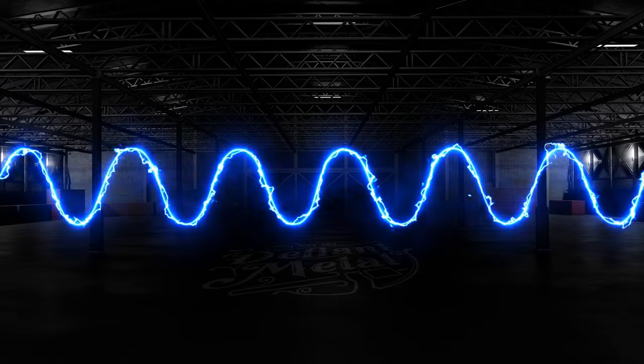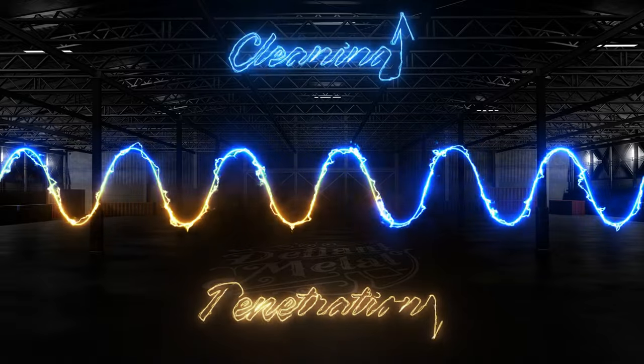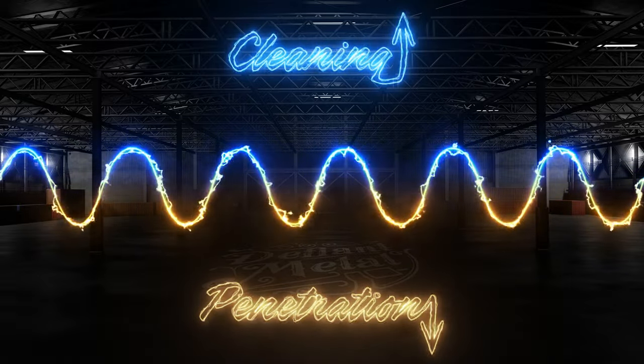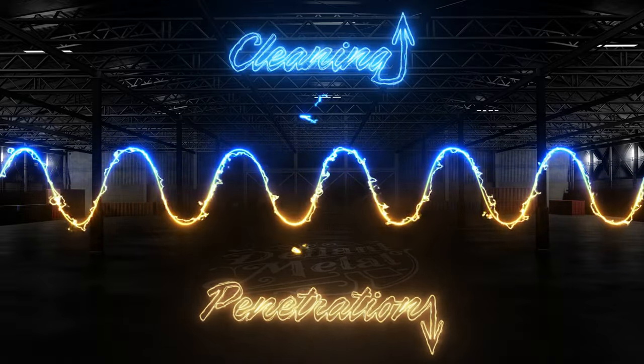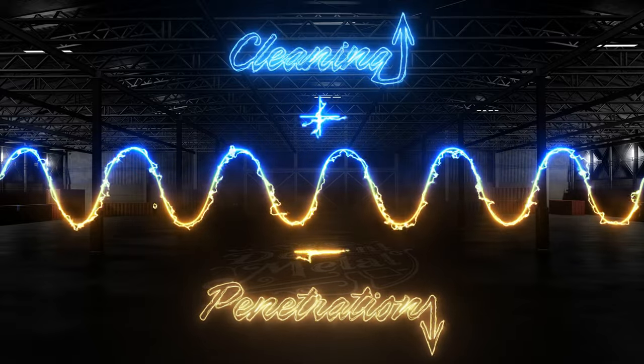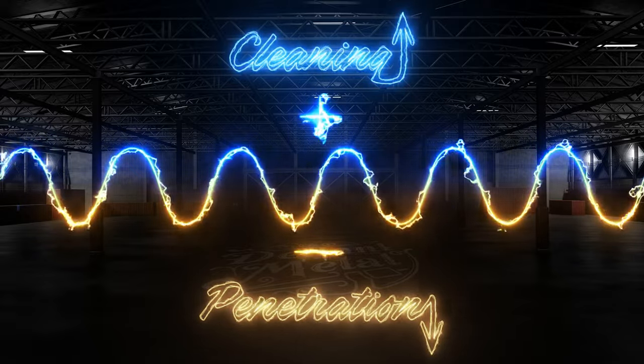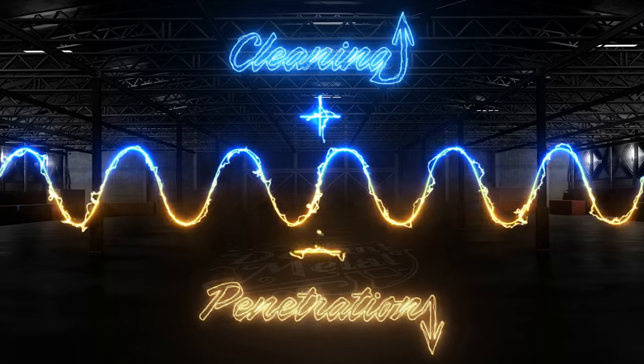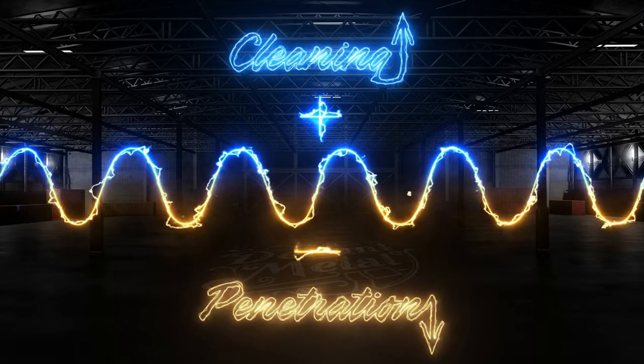This is where the negative side of the cycle comes in. Making the tungsten electrode negatively charged and the aluminum positively charged, now the current and heat flows from the tungsten into the piece that you're trying to weld. This not only gives you that penetration that you need for a strong weld, but it also helps keep your bead narrower and the etch zone on each side smaller, if that's something you're into.